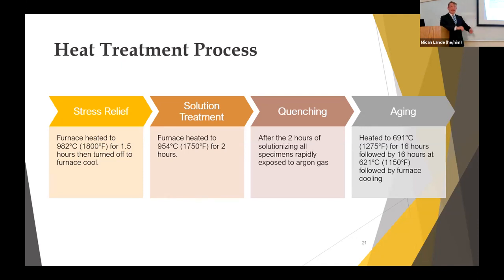Afterwards, it's boosted back up to close to the same temperature, but for just a little bit longer in order to solution treat. And then while those samples were still red hot, orange hot, white hot, they were pulled from the furnace and immediately sprayed with argon gas in order to quench them as fast as possible. And then after that, they're thrown back into the furnace for another 16 hours at a lower temperature, and then furnace cooled again to a slightly lower temperature for another 16 hours, forcing me to come in at 3 in the morning several times to make sure the furnace actually changed temperatures. That was fun. So either way, at each one of these steps, we have samples being taken out so we can see how things change throughout the heat treatment process.